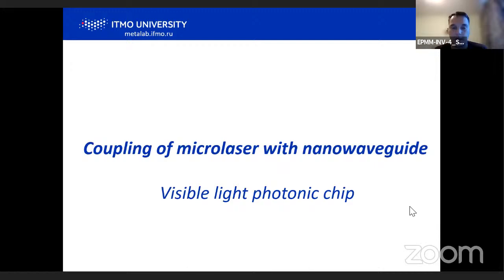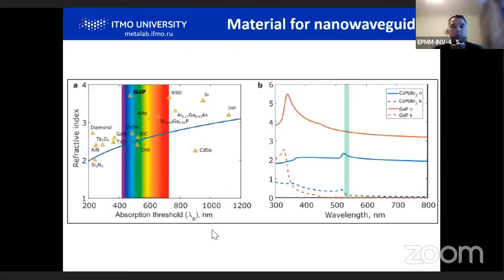And once we can create perovskite lasers, nanolasers, microlasers, it's tempting to integrate them with nano waveguides. So what is the best material for waveguiding in the visible range? Of course, it's not silicon, because silicon has very high losses in the visible range.